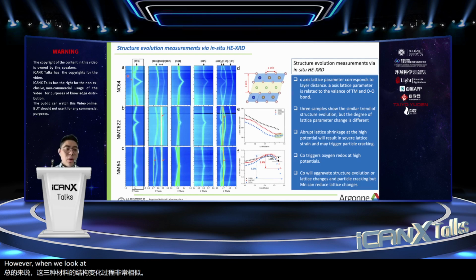However, when we look at this O3 peak, you will see these three materials show very different degrees of lattice parameter change. For example, this nickel cobalt 64 shows a left shift for the lattice parameter, the c-axis parameter, and then quickly shifts right. This right shift of the lattice parameter means they will have a very fast or abrupt lattice contraction in the high voltage. And then when we reduce cobalt with manganese substitution, we will see this right shift of the lattice parameter get reduced a little bit, and then when we completely remove cobalt from the NMC cathode, we will see very small peak shift in the high voltage. So basically, cobalt will trigger the huge lattice parameter changes, and manganese can suppress these lattice parameter changes.